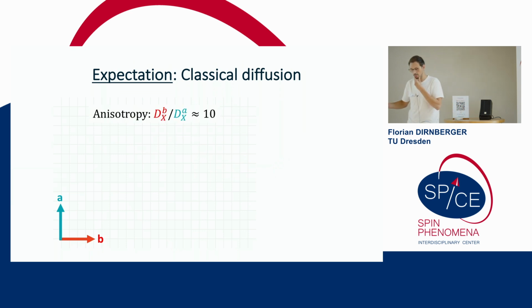Just to very briefly introduce the way that we do this experiment: in most semiconductors, when we create excitons, the typical process by which they move is classical diffusion. It is very much the picture of a drop of ink in water that just disperses over time. This is just diffusive transport. Because the masses of electrons and holes are anisotropic in this material, we can calculate the anisotropy ratio of the diffusion coefficients. We expect that within the plane, along this easy axis where the effective mass is fairly light, we get a 10 times higher diffusion coefficient than along the other direction. So we expect this anisotropic diffusion.